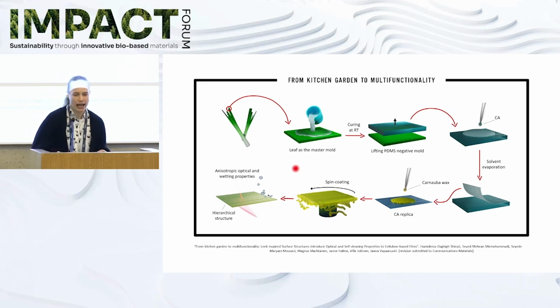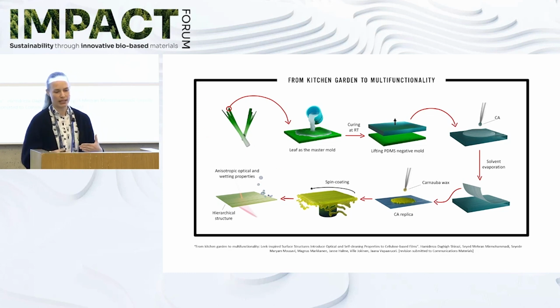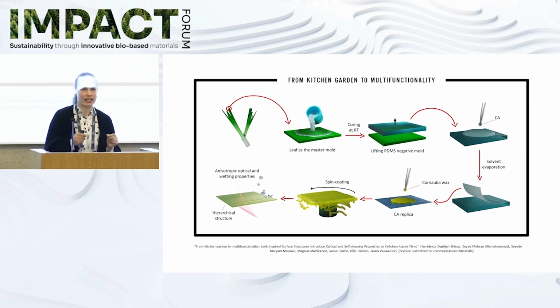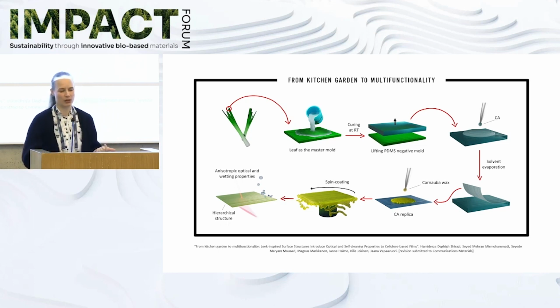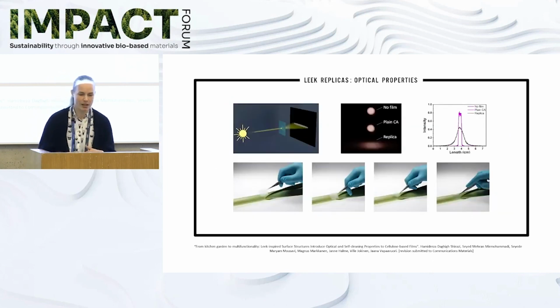What we then did at the lab was that we developed this type of very easy soft lithography process where we can imprint the leek surface pattern on cellulose acetate. And then, because the leek surface actually has a very hierarchical structure, we add one level of hierarchy by spin coating carnauba wax on top of the cellulose acetate. And here are the films.